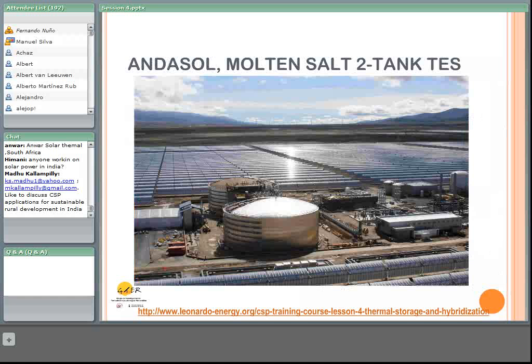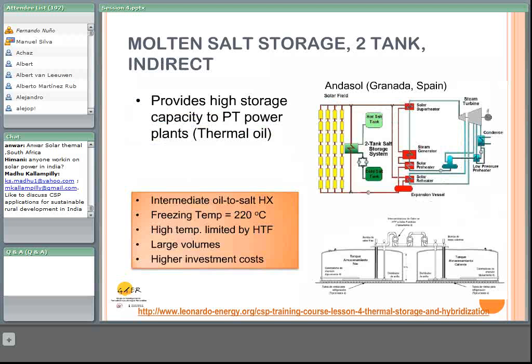As I mentioned, the thermal storage capacity of the Gemasolar plant is roughly the same as that of the Andasol thermal storage system, but because the delta T between the hot and the cold tank is more than double that of the Andasol, the volume of salts is approximately 1/3 of that of the Andasol plant. Therefore, the cost per kilowatt hour stored is much less. It's considerably less than that of the Andasol plant.